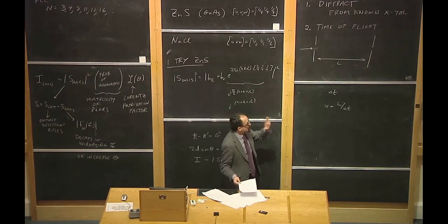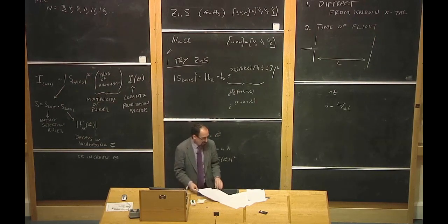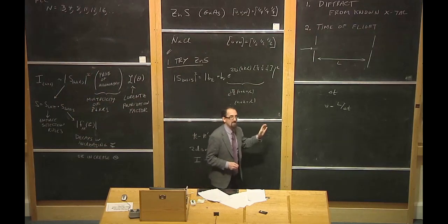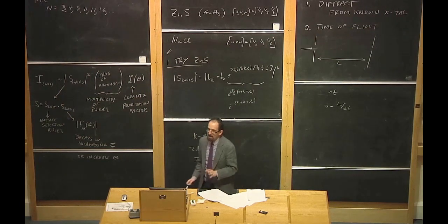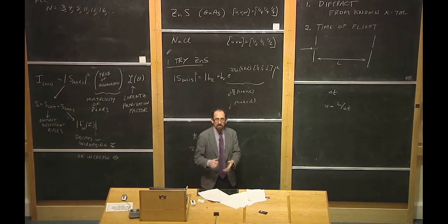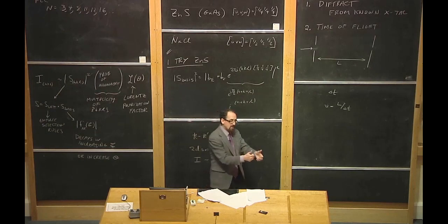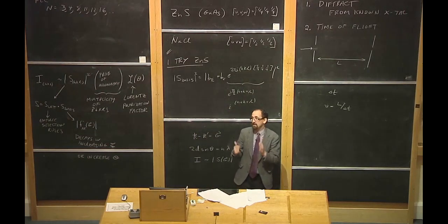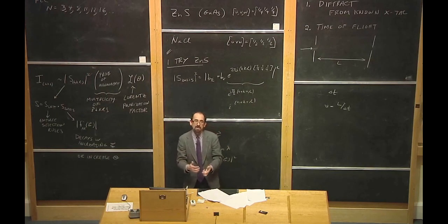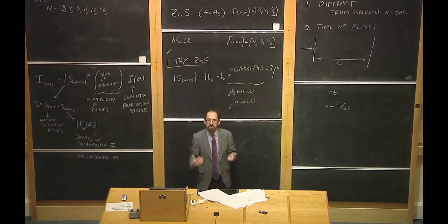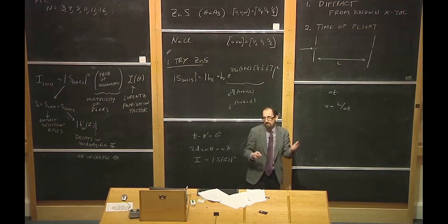One more thing that I do want to mention about neutrons, we'll say maybe just one or two more things about them in the next lecture, but I do want to mention now, is one of the reasons people like neutrons is that neutrons actually have a spin. And that enables you to see things where the spin is important. If you have more spins in one region than another region, the neutrons are sensitive to that. They feel the local magnetic environment as a potential, whereas photons do not. They don't care about the local magnetic environment. Neutrons do because the neutrons have some spin.